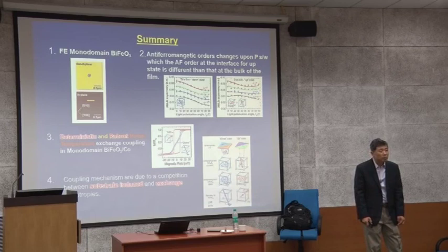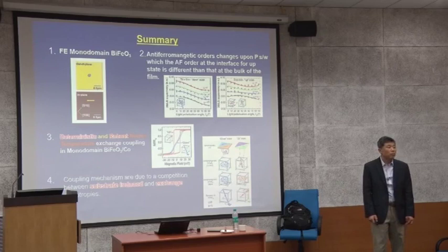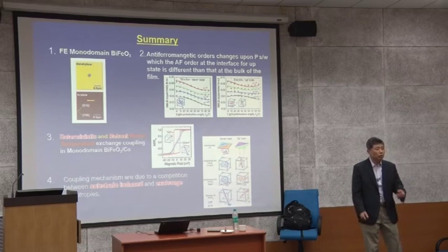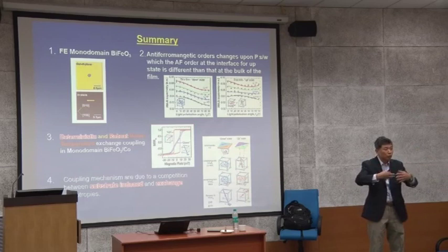This MH loop shows the anisotropy of the cobalt, in plane. It's a MOKE measurement in plane. Do you know the MOKE measurement? Magneto-optic Kerr effect. It's a MOKE measurement because it's surface sensitive and magnetic. We want to measure only regions of the electrode, not the whole thing. You switch that, so you have to focus the laser beam to look at those regions of the device.